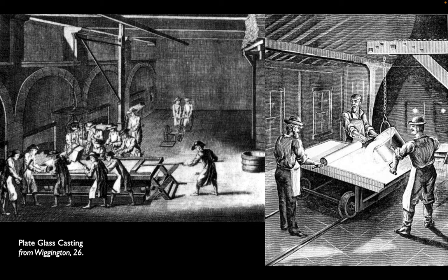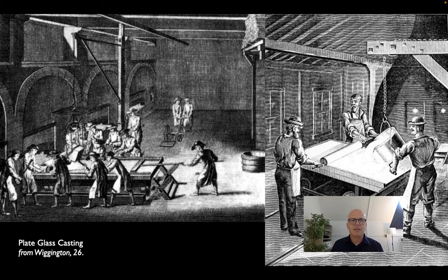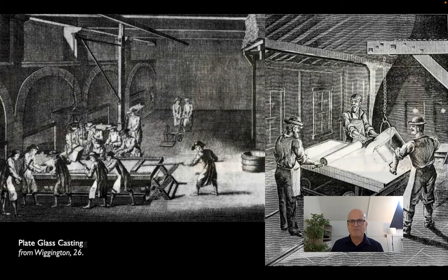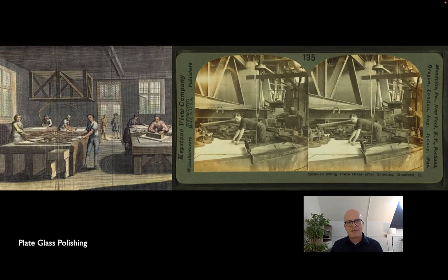The surfaces are rough, but the material in the middle is perfectly fine. And so you take that piece of glass to another workshop and you grind off the rough surface and then polish the resulting smooth surface. And this gives you a finish and a surface that's virtually perfect, right? You can get this as smooth as you want, and therefore you can get the glass almost as transparent as you want.